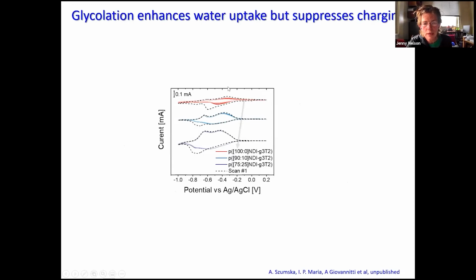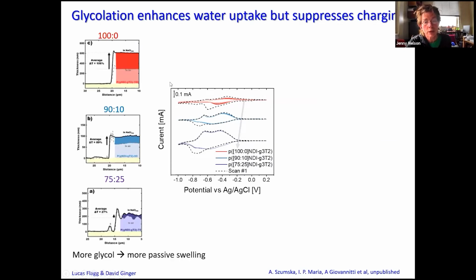There's a small shift in the oxidation potential to more negative potentials as you increase the amount of alkyl in the polymer, and it becomes less polar, I suppose. That's more or less what you would expect if you think about what will happen to the dielectric constant of the environment. It's also what you would expect if you look at the interaction of the polymers with water. Because we also measured, and this was a collaboration with David Ginger's group, the take-up of water in the polymers, and even the passive swelling of the polymers is strongly dependent on the type of side chain. So the fully glycolated polymer swells a lot, and then the partially alkylated polymers swell, but not so much.